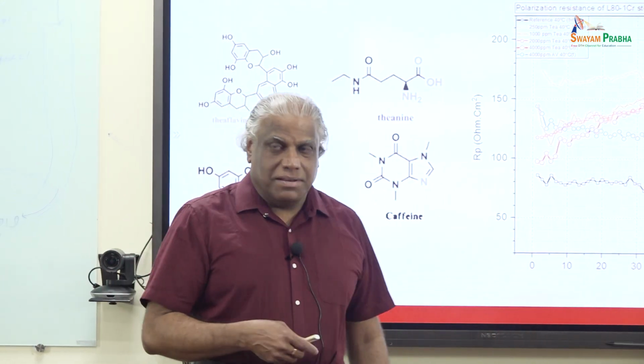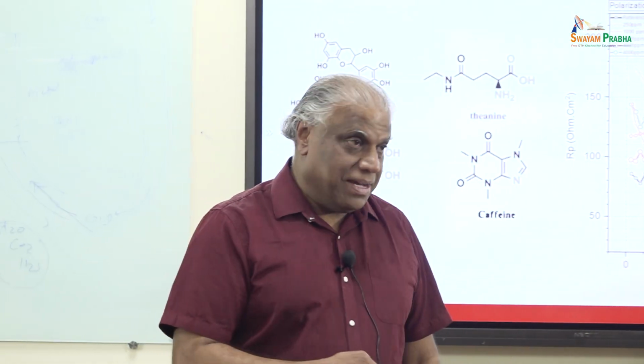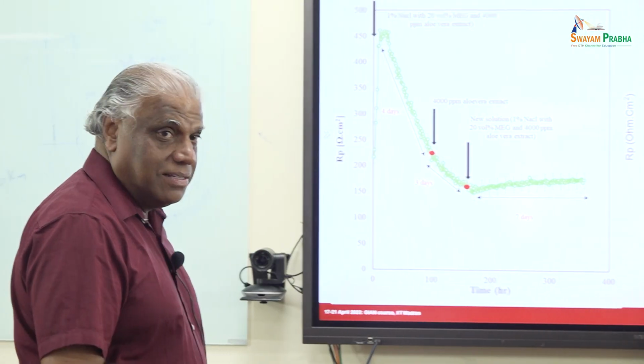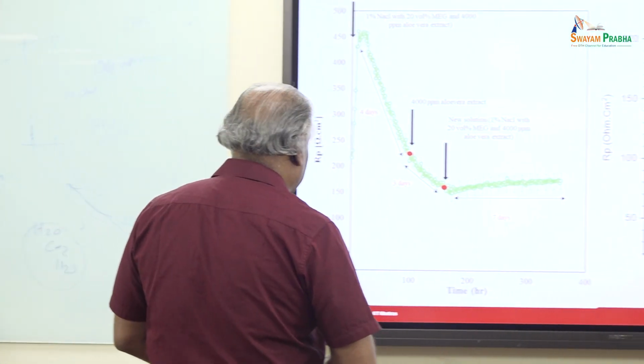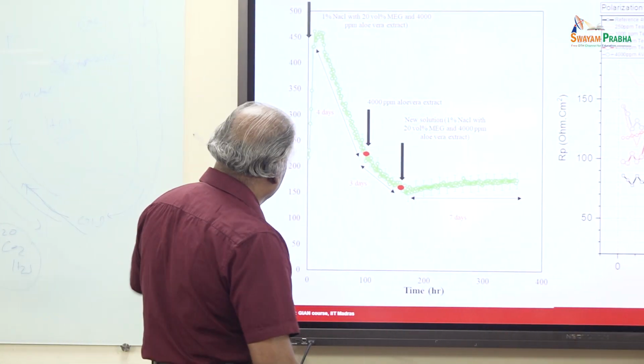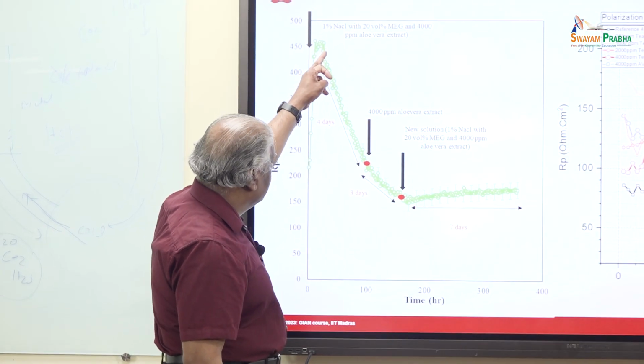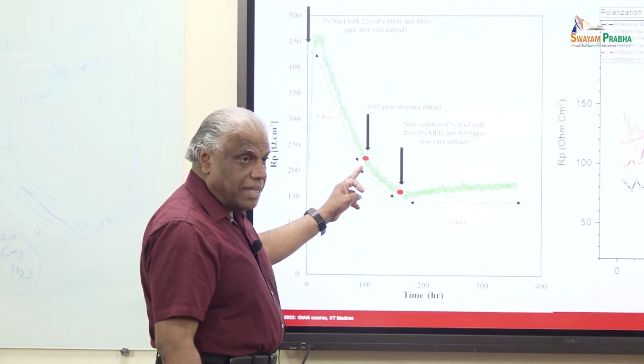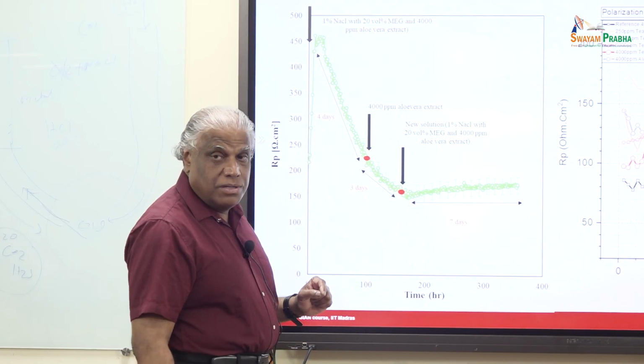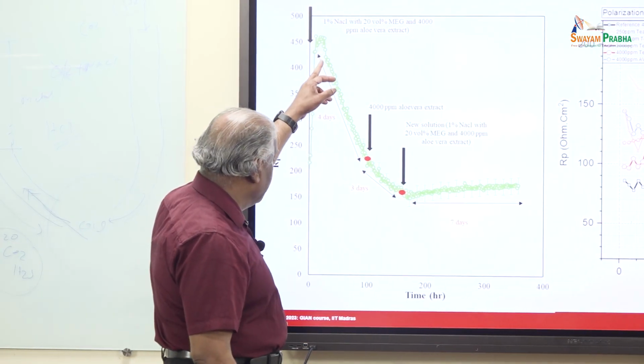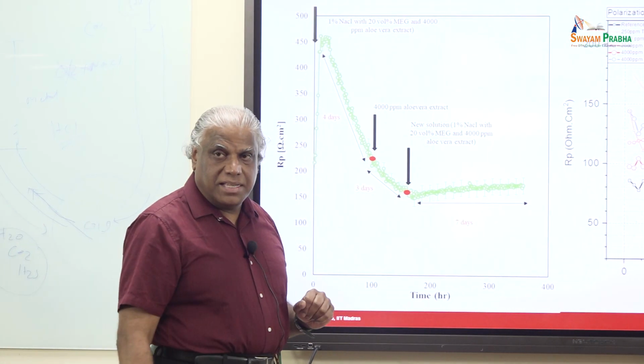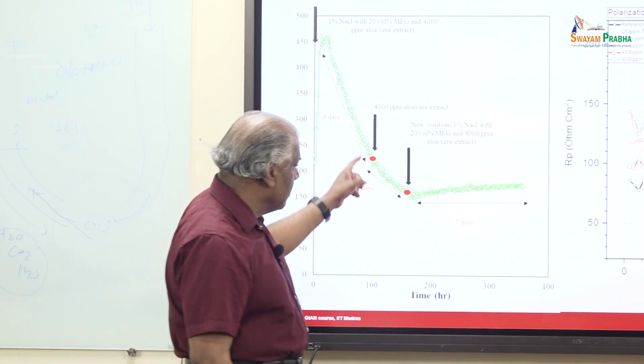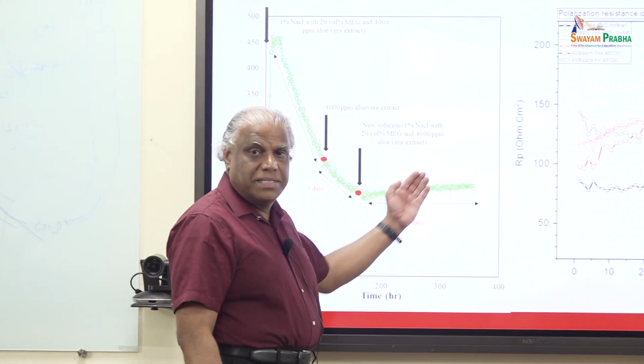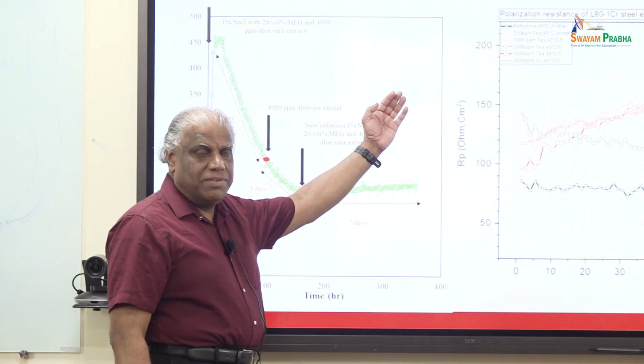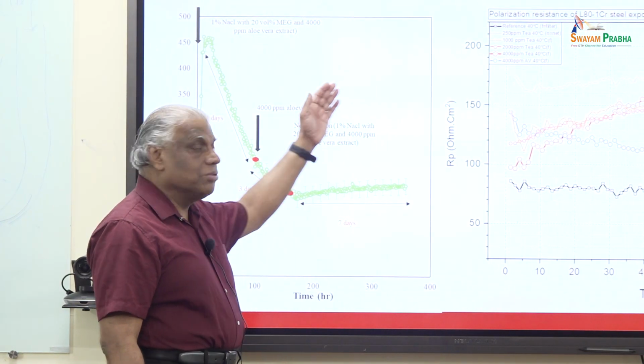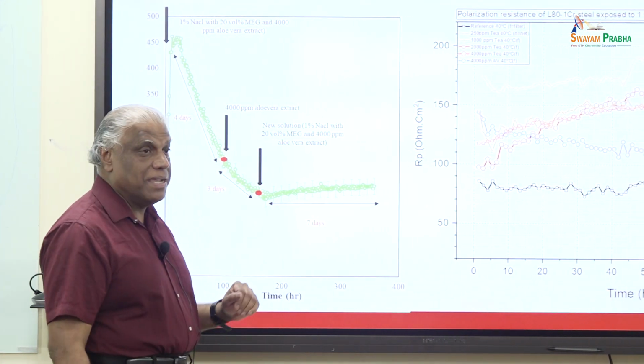Now we are trying with aloe vera, and there was a problem we found. The problem with aloe vera is that it gives 88% inhibition, but inhibitor efficiency drops very much after 4 days. So for 4 days it works. After about 4 days, the efficiency decreases very much, which means that you need to inject it again to bring it back to the level. And that's also not good, because then the injection frequency has to be higher.